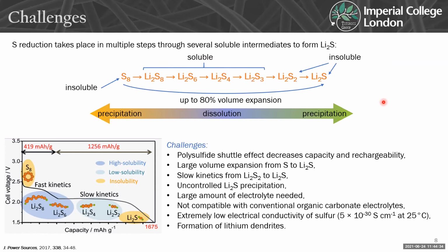And if they end up depositing elsewhere other than the cathode, it means that we've lost capacity from that shuttling effect, and that obviously affects the long-term cycling ability of the battery. And because again the reactions happen in the electrolyte, you need quite a large amount of electrolyte in the solution, and it's not compatible with conventional organic carbonate electrolytes that are found in lithium-ion batteries. So alternative systems need to be found.